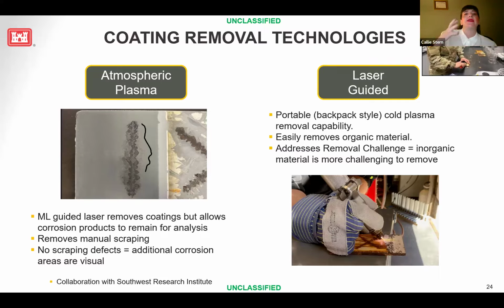And as soon as it hits some form of corrosion, it will stop so that we can move forward and analyze that. So this laser guided process removes the need for manual scraping and is also able to expose corrosion. This is really cool. If the coating is delaminating and we have corrosion in the middle of a delamination, we can figure out at what layer the corrosion is happening. What is going on? Is there proper adhesion? Is there not?